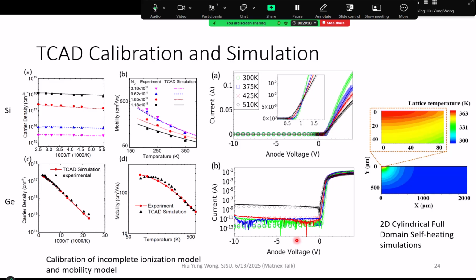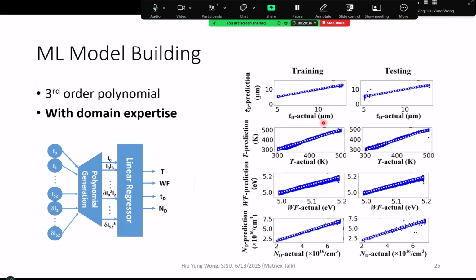The only message with what we try to do here is just that our simulation is very accurate. We calibrate the carrier concentration and mobility model well to other experimental data. We calibrate the forward IV and reverse IV well to our experimental data. And we perform a 2D cylindrical simulation, which is equivalent to a full 3D simulation with self-heating. And this matches the experimental data very well. So we trust that our TCAD calibration and simulation are good.